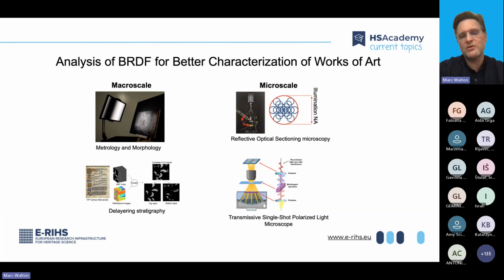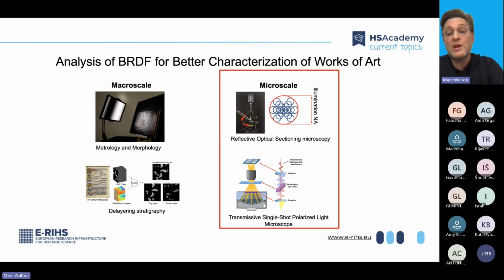The other is to be able to think about combining together different modalities of light. So for instance, I'm showing you here in the lower left-hand corner, if you were to combine together, say, an X-ray fluorescence cube with a reflectance image cube, you can exploit the different amounts of penetration that they would have into a painted surface energetically to be able to do source separation. So you can look at hidden layers or hidden features by finding some way of algorithmically combining them together. The organizers of this current presentation, however, asked me to talk about some of the work that I've been doing at the microscale.